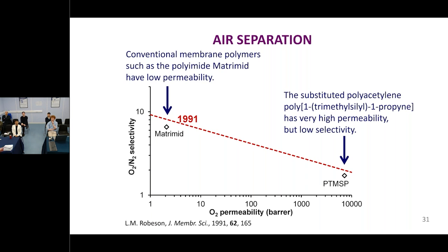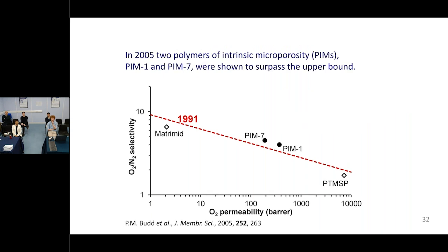And after 1991, really there was not much change for quite a while. And then in 2005, when we first produced PIMs, we didn't have the facility to do gas separation measurements. So we collaborated with Detlef Fritsch at what was then known as GKSS, one of the Helmholtz centers in Germany, where they have a lot of experience in gas separation. And so in 2005, we published the first gas separation data and demonstrated that two PIMs, PIM-1 and another one, PIM-7, were much more permeable than most other polymers, and that they broke that 1991 upper bound.